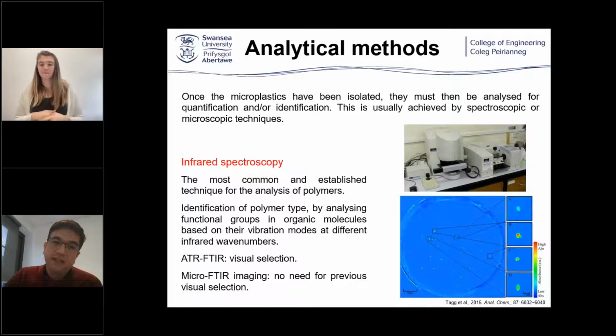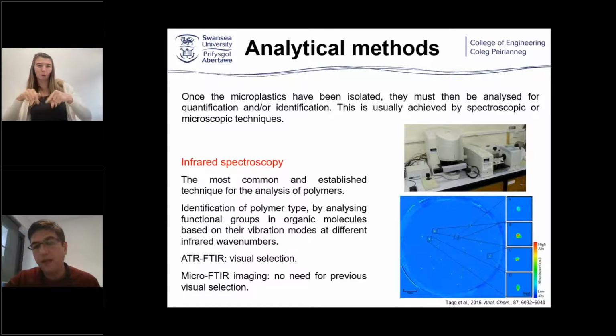The most common technique is infrared spectroscopy. It's one of the most common and established techniques for the analysis of polymers. So the spectrum of different polymers is already known with infrared spectroscopy. Therefore, you can identify the polymer type by analyzing the different functional groups in their organic structure. And with the use of micro FTIR, you can also get the size and the morphology of the plastic, and you can count them. For example, here you can see a photo of a filter membrane with different microplastics, and based on the spectrum that they have, you can also get the identity of those polymers.